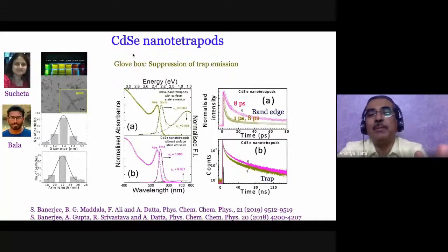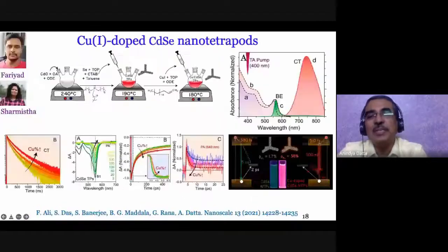And we could prepare two kinds of nanocrystals by playing around with the conditions. And we learned how to make them strongly photoluminescent or weakly photoluminescent. The problem was that even the best nanotetrapods that we prepared had really weak fluorescence, weak photoluminescence quantum yield. 0.06 is nothing to write home about. So we decided to try a new strategy.